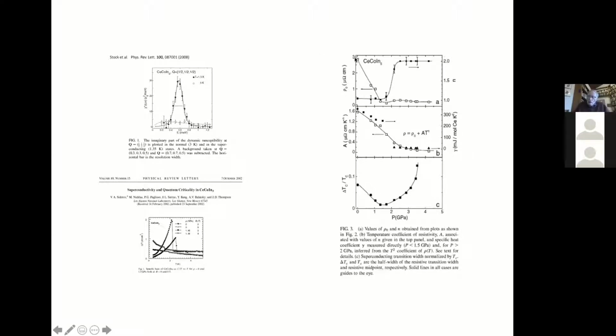this extrapolated resistivity here actually corresponds to something like 30% of this magnetic spin fluctuation resistivity that exists at the coherence temperature, and this is disappearing as one goes down with pressure here. And so the idea is that cerium cobalt indium 5 still has essentially some of this spin.